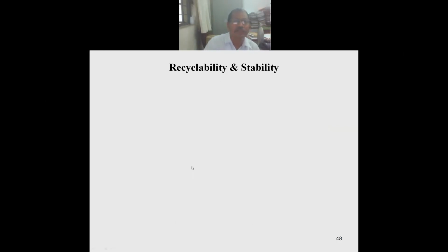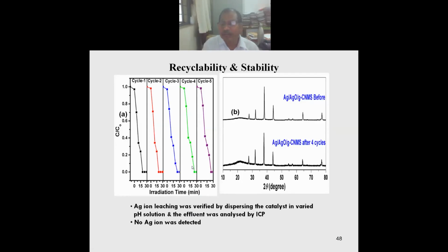degradation efficiency. Again, recyclability is very important for a catalyst, and the experiment is performed. After each experiment, the catalyst was separated, washed clean, dried, and reused for another cycle. In this fashion, the same catalyst was used for 5 cycles, and the powder XRD pattern is taken again.